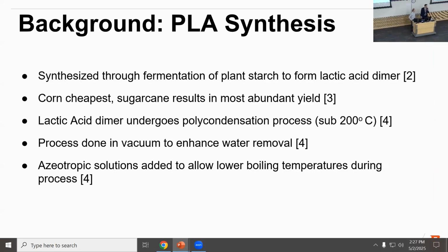So a little bit of background on PLA. It starts by being synthesized through the fermentation of plant starch to form lactic acid. In the States, it's most commonly corn. In other areas like Southeast Asia, sugar cane gets you your most abundant yield. This lactic acid dimer then undergoes a polycondensation process at temperatures below 200 degrees Celsius. This is also done in the presence of an azeotrope and in a vacuum, both of which are to further enhance the water removal.